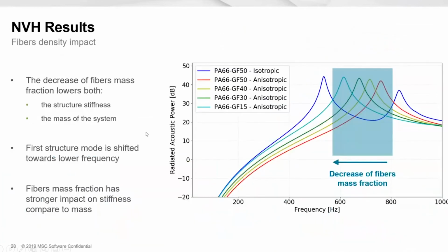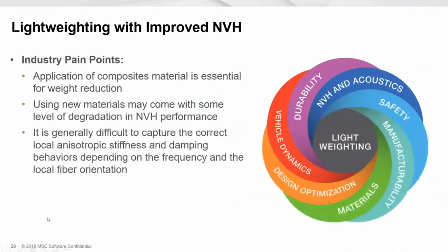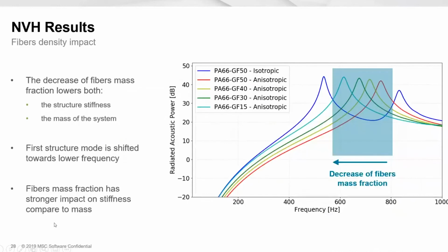So we are simulating the injection process, but with different percentages of fibers. And here again, we can see a huge dependency of our response on the fiber density. In particular, we see that as the fiber mass fraction is decreasing, the modes of the structure are shifting to lower frequency. And this is directly reflected in the radiated acoustic power.